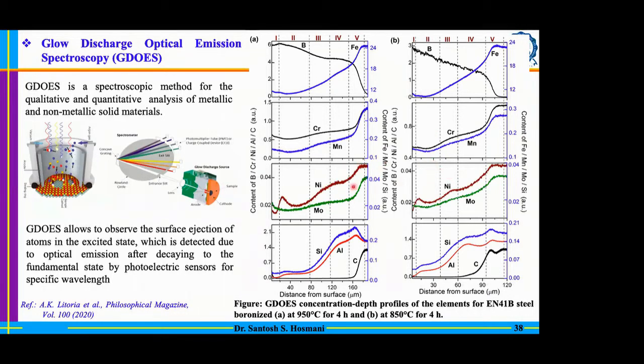That means it's not by accident that we have got this particular profile. The system is really following some kind of mechanism here, and that mechanism is consistent. I will show you different durations too, and there also it follows a similar trend. That means something is happening with respect to the migration of the elements and the growth of this particular boride.